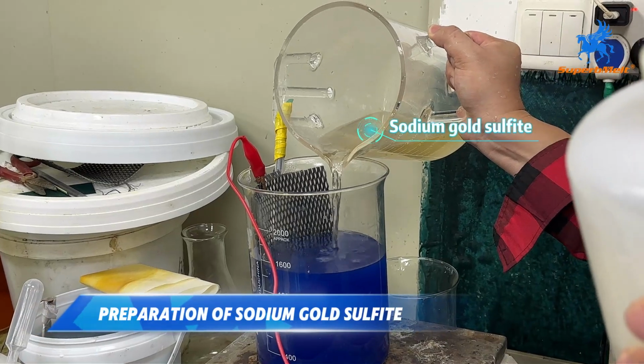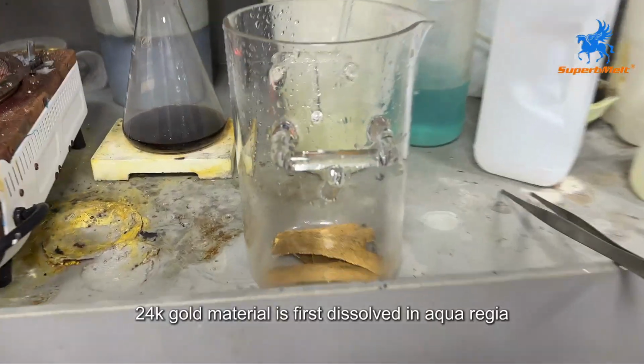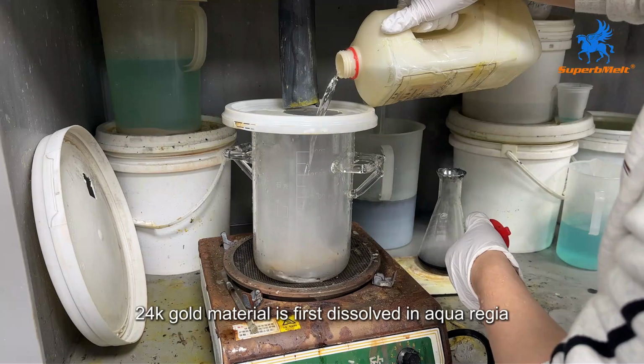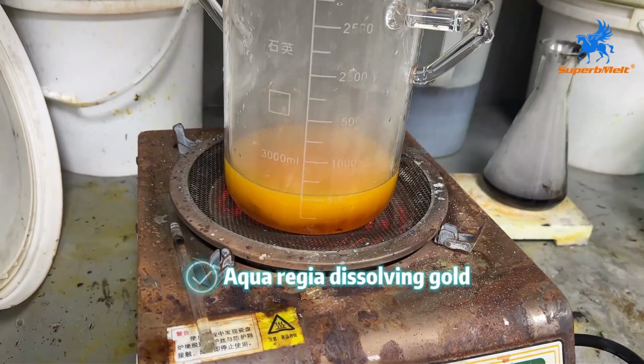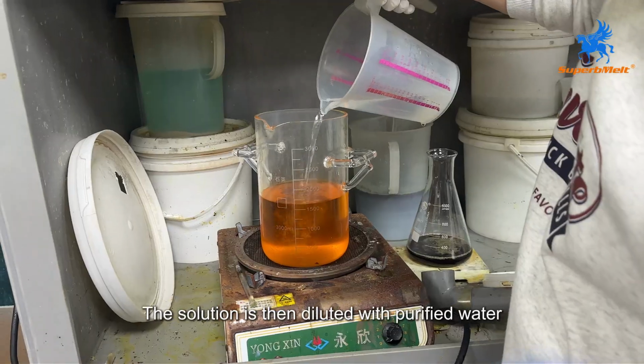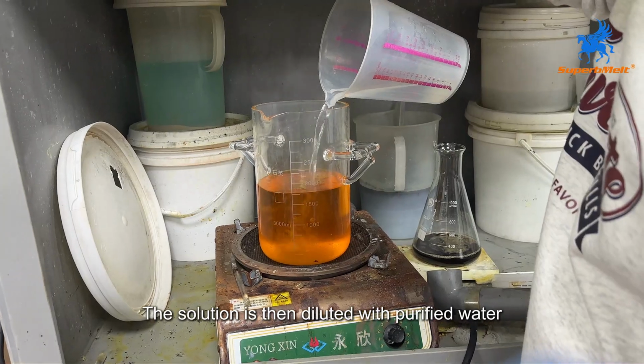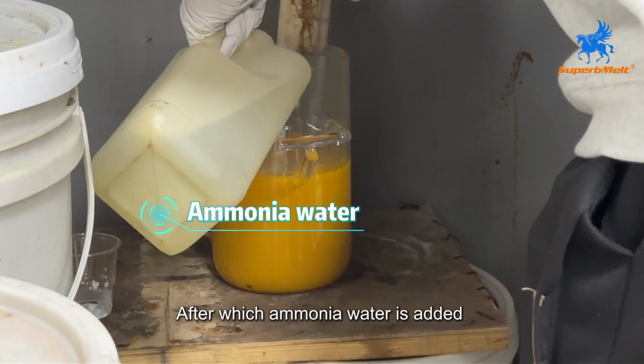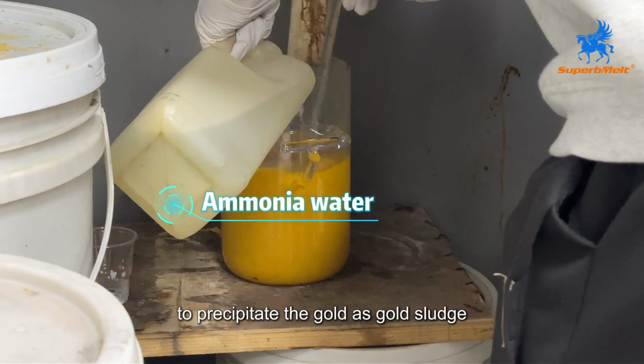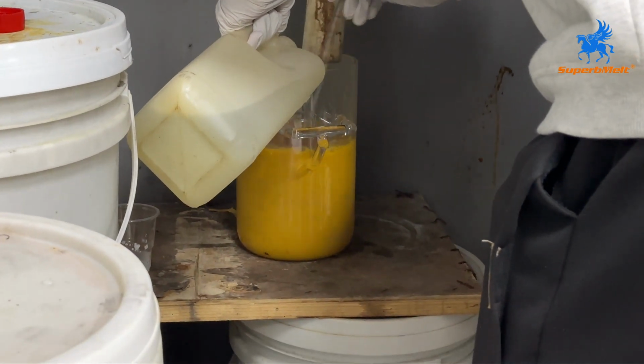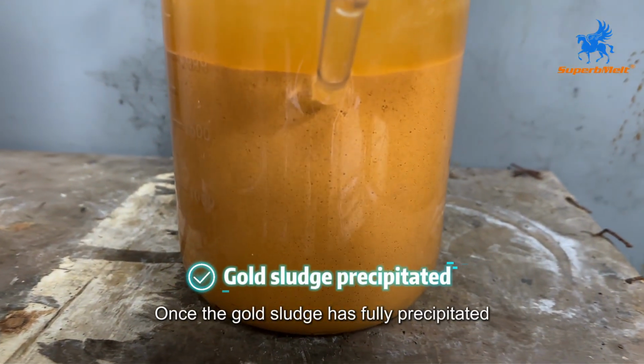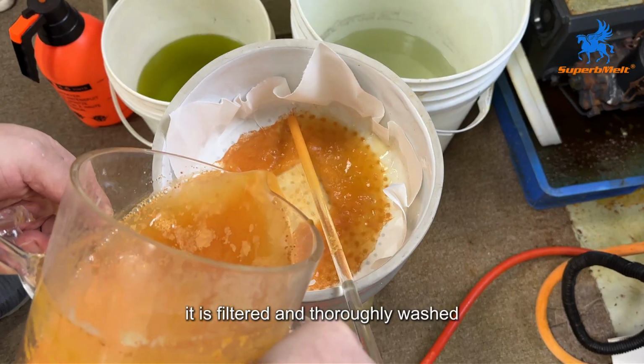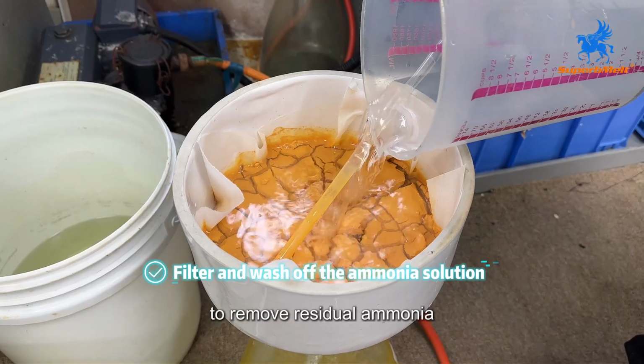Preparation of sodium gold sulfite. 24K gold material is first dissolved in aqua regia. The solution is then diluted with purified water, after which ammonia water is added to precipitate the gold as gold sludge. Once the gold sludge has fully precipitated, it is filtered and thoroughly washed to remove residual ammonia.